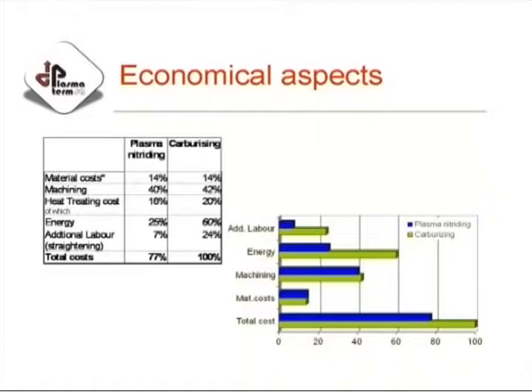And there is an important aspect to emphasize here, a real practical one. You know that different lots of steel from the steel mill will come with slightly different properties even inside the standards. And these slightly different properties sometimes influence the carburizing and the results of carburizing rather strongly. Such an influence has never been found in this case of plasma nitriding or plasma nitrocarburizing. So which is also a very big advantage, because that means for a really very important, very accurate, and very high precision part, the considerations for the steel quality are a little bit less important than for carburizing. So this is, from economical point of view, very important.